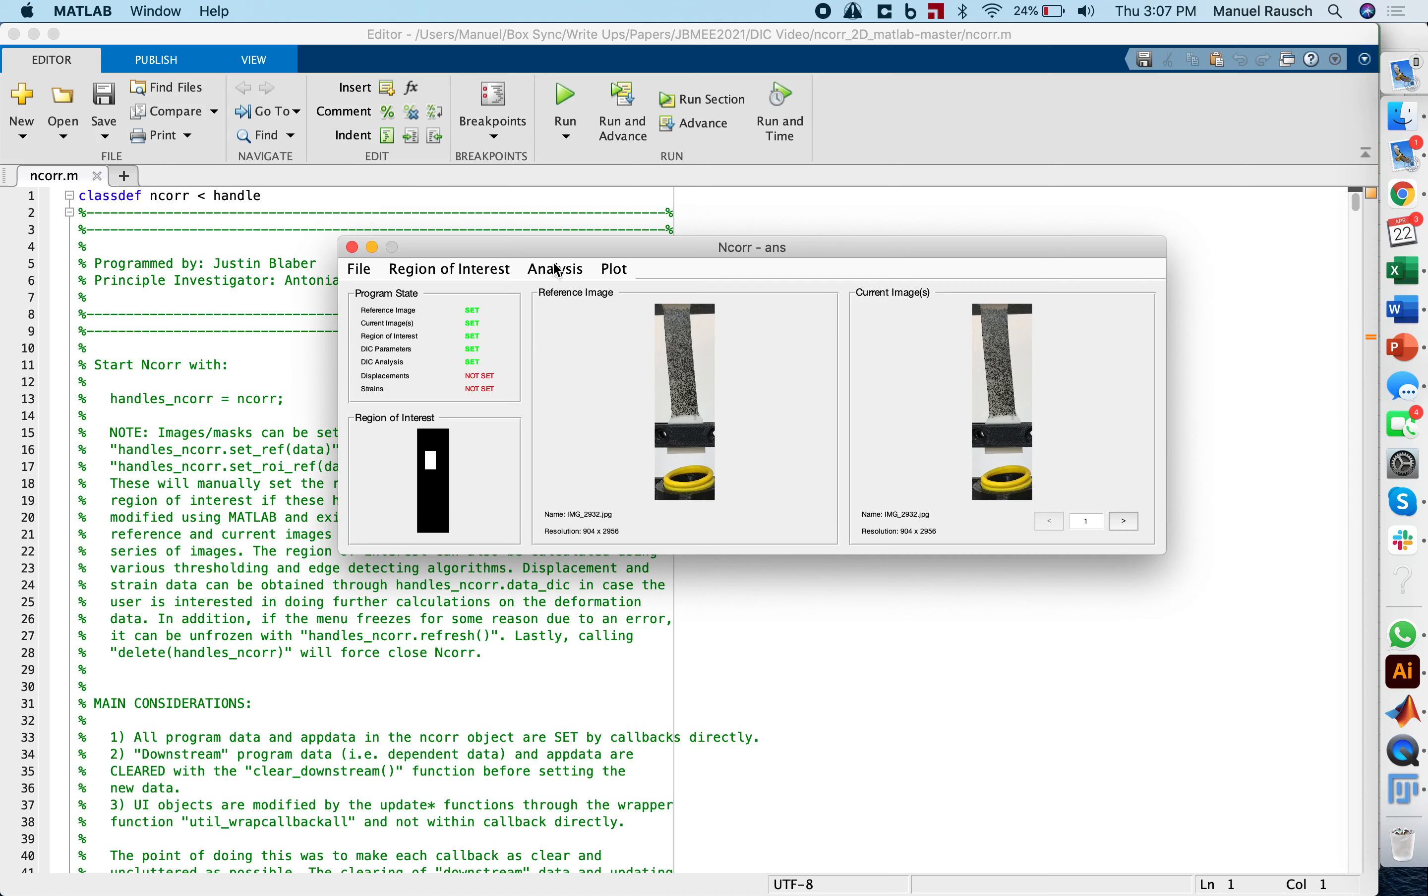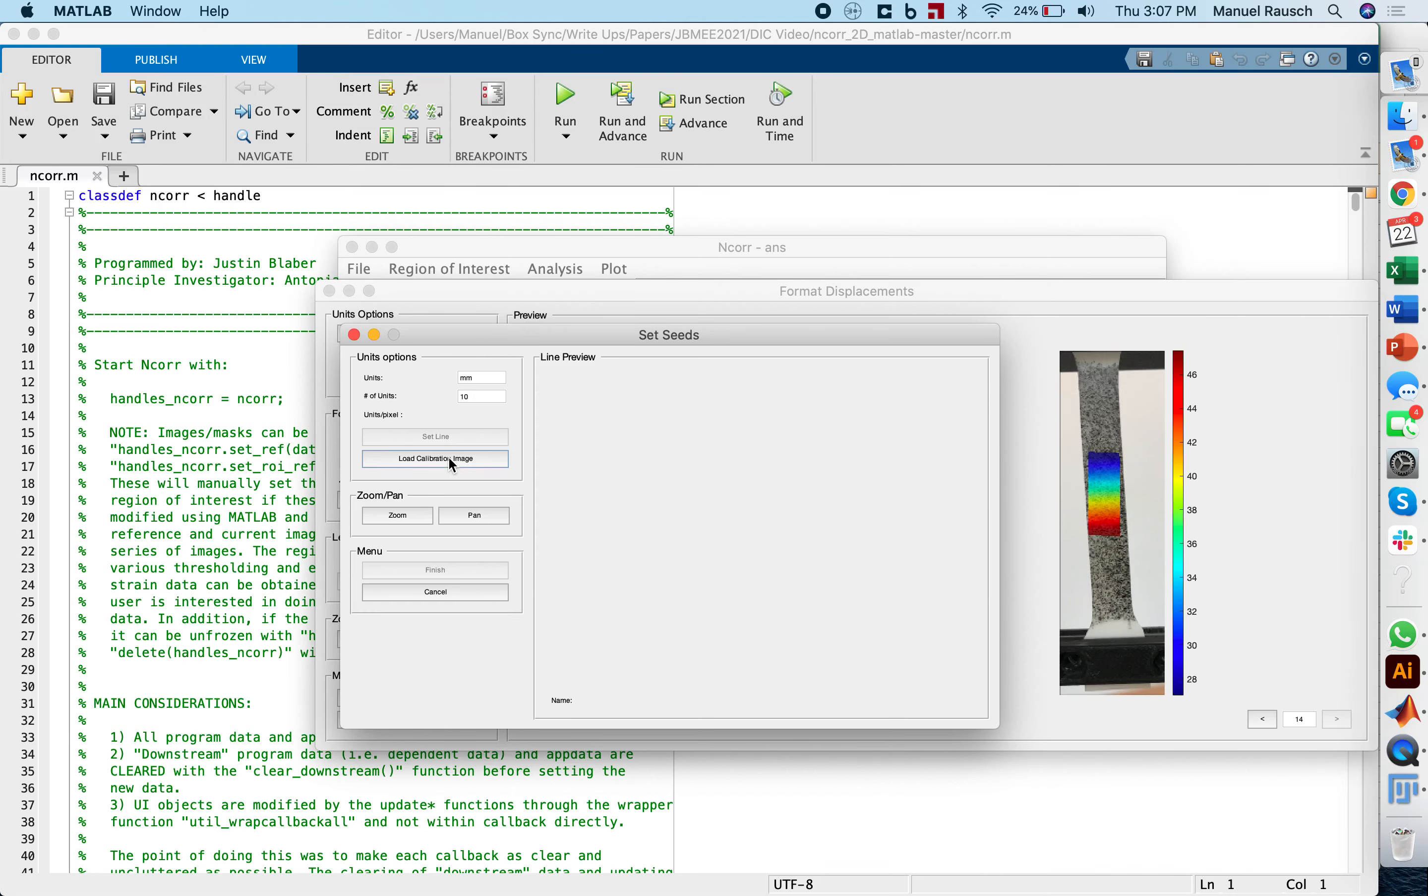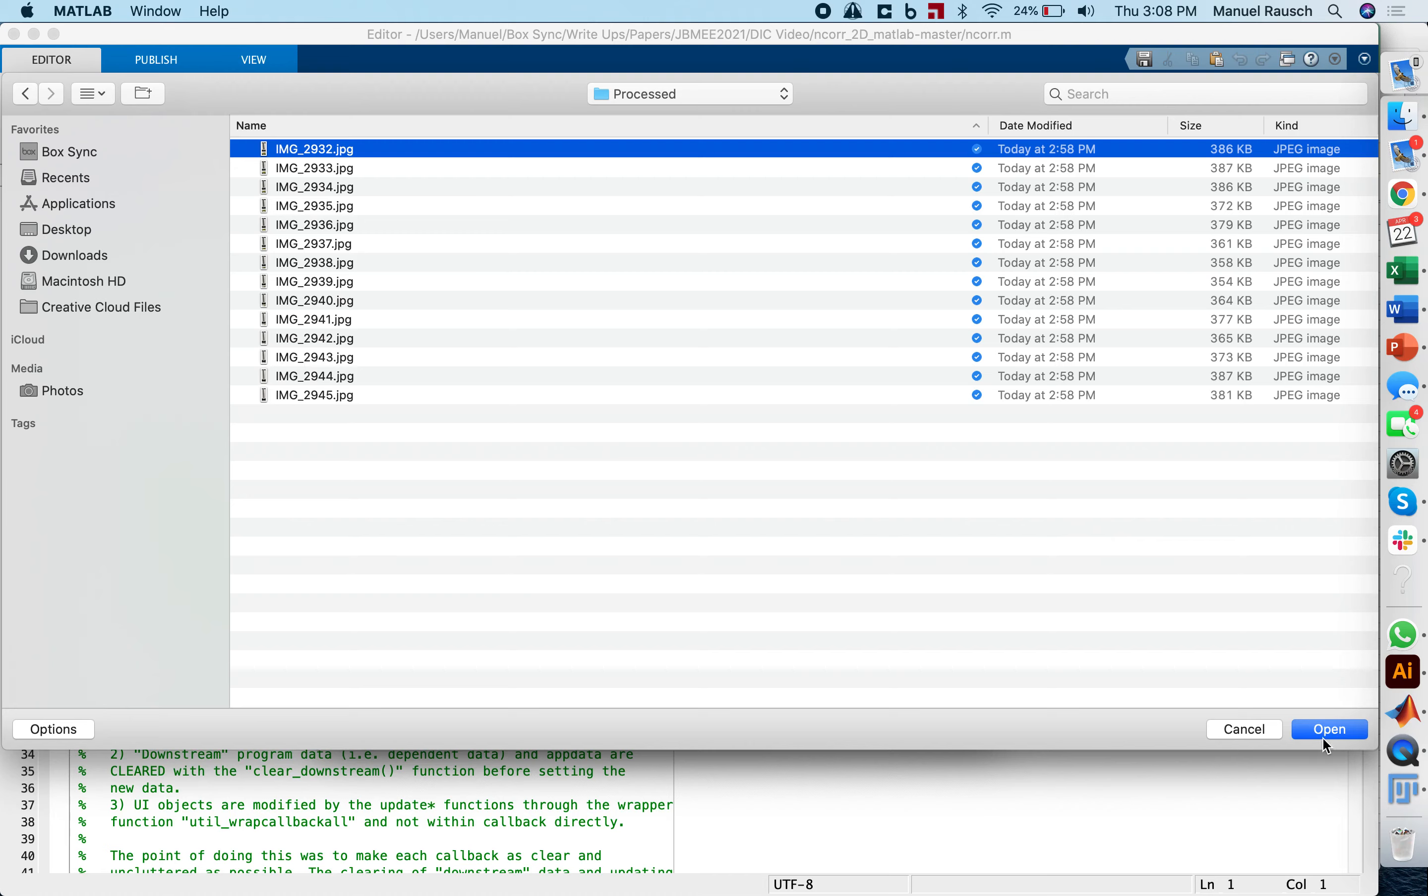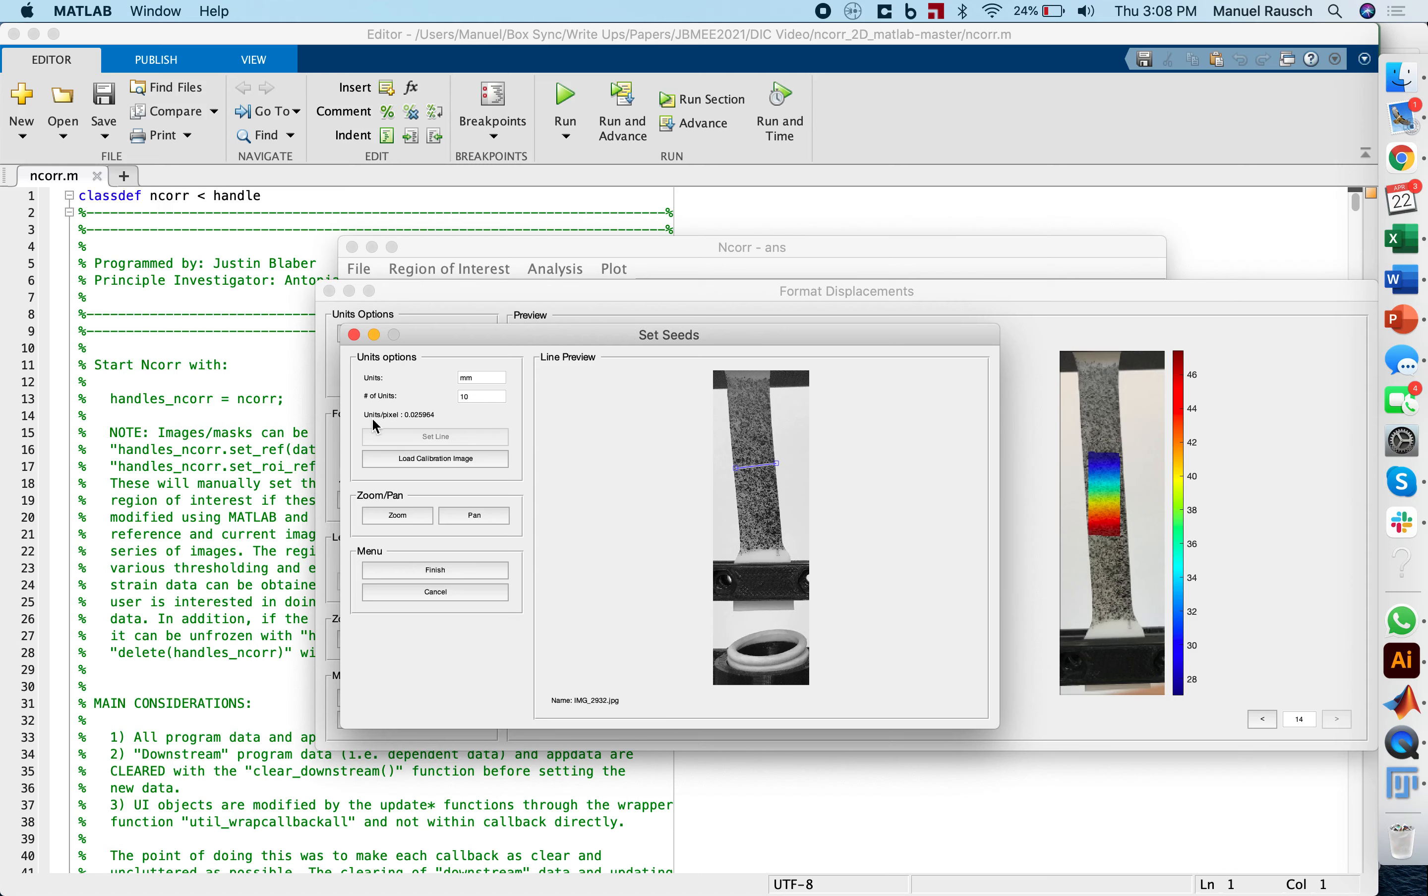The next step will be displacements. So under analysis, we can now compute displacements. This step essentially assigns physical dimensions to our currently dimensionless analysis. When we click get unit conversion, we can now actually define a reference line and give it a physical dimension. To this end, we can load a calibration image. What this really means is that we're going to load an image of which we know the dimensions. It turns out that of course, when I made the sample, I defined the dimensions to be specifically 10 millimeters width. My dog bone sample has a width of 10 millimeters. So I can now set a line. I draw a line along the width. The sample is a little tilted, so I tilt my line as well. And I define this to be 10 millimeters. And now the code can actually define the length of a pixel, which happens to be here 25 micrometers.